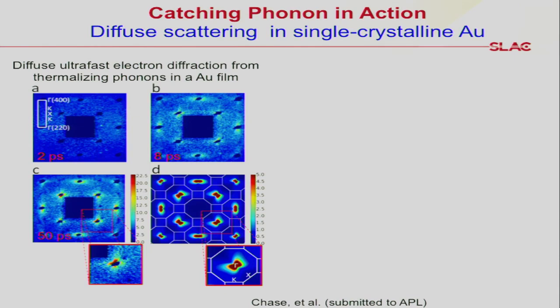So the first system we look at is gold. X-ray people really like diamond, but we like gold because you can buy perfect crystals commercially. And we use a laser to heat the gold. Then we look at these Bragg peaks, and between the Bragg peaks, how the diffuse scattering evolves. This is 2 picoseconds after the laser hits the sample, 8 picoseconds, 50 picoseconds. At the beginning, there's nothing between the Bragg peaks. As time evolves, more structure shows up. That's where the phonons are, and also around the Bragg peaks.